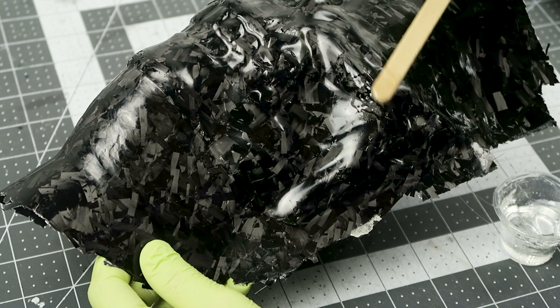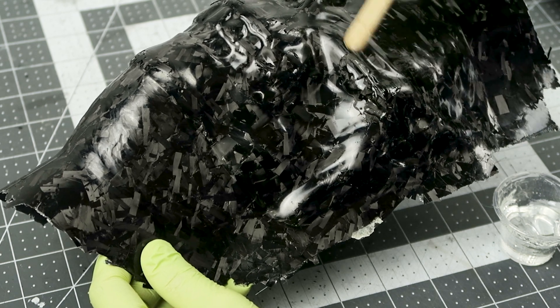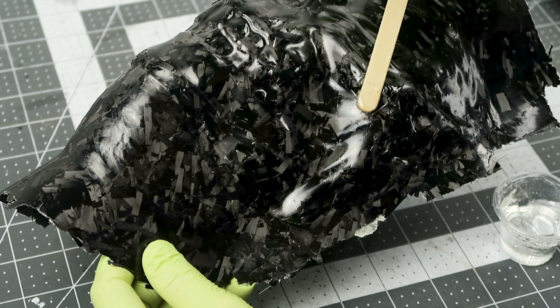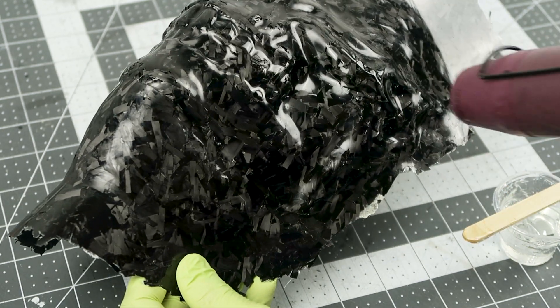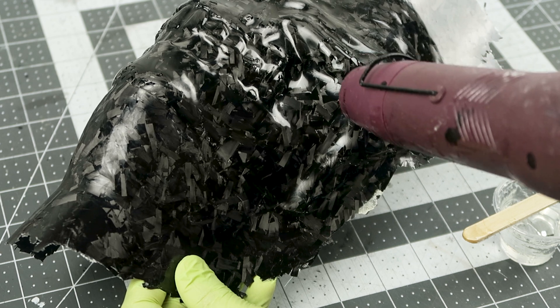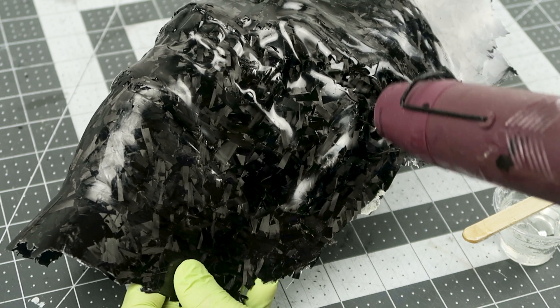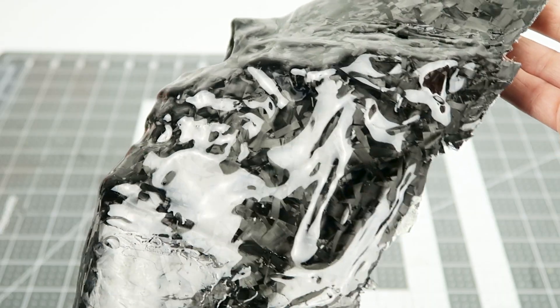There's a consistent full gloss finish over the entire piece. If you attempt to do this with epoxy that's not partially cured it will need to be done in multiple layers and take quite a bit longer. Plus this is completed with no sanding. Imperfections are simply filled in with thickened partially cured epoxy.